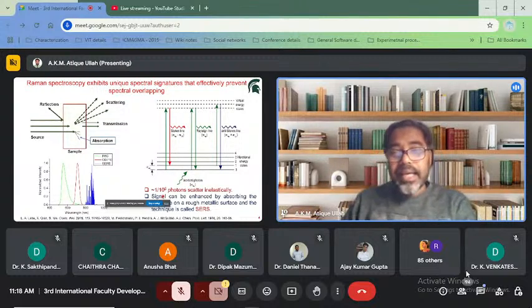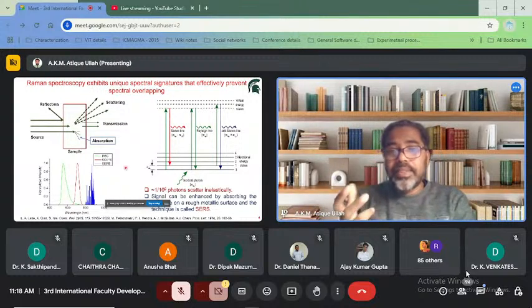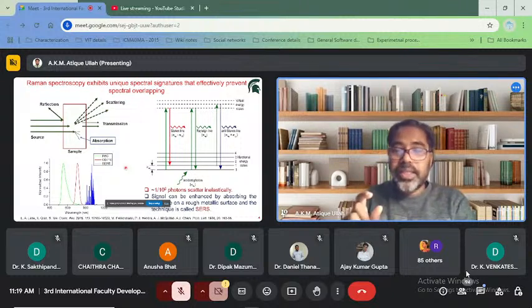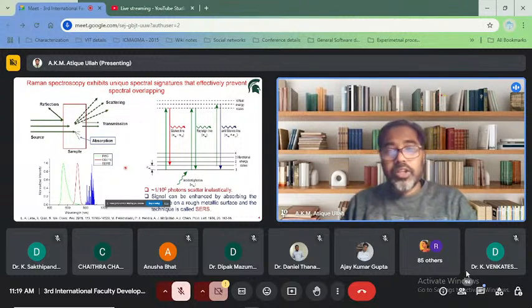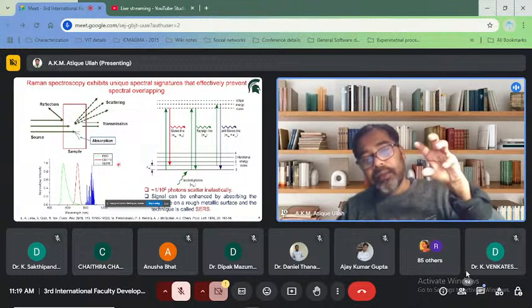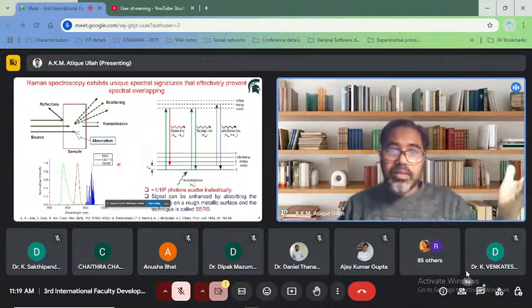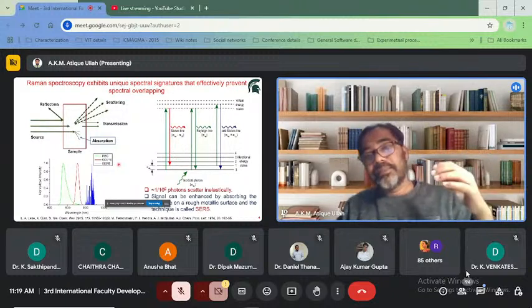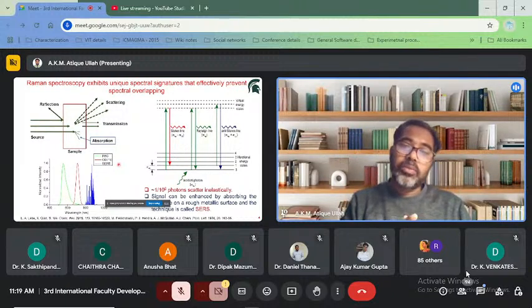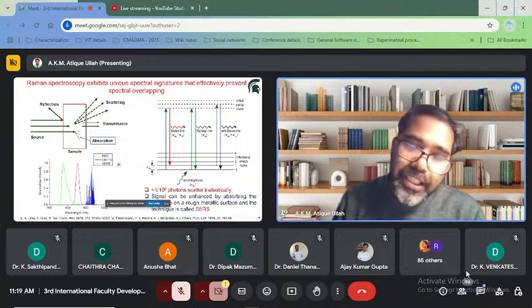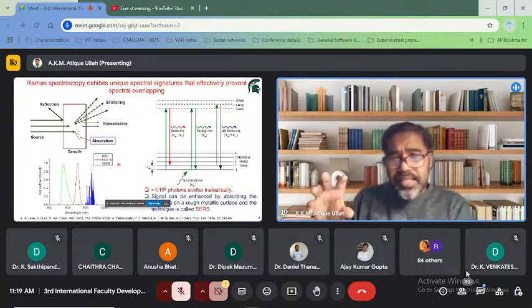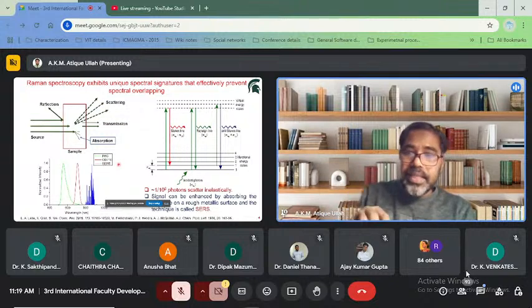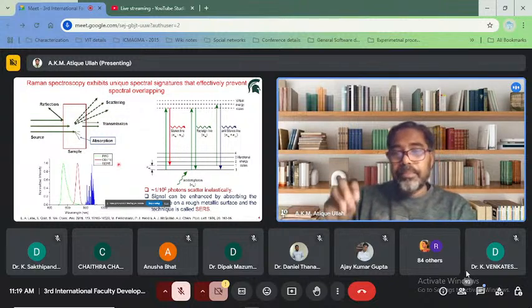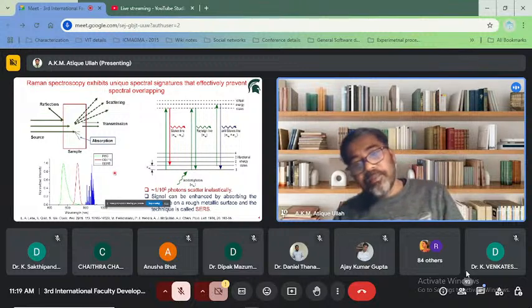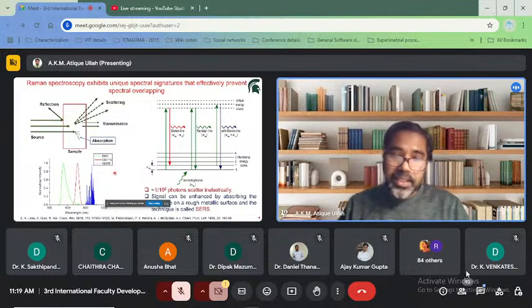This signal can be enhanced by certain techniques. If we put a Raman active molecule on the surface of certain nanoparticles such as gold or silver, the signal can be enhanced, theoretically by almost 10 to the 14 times. Since it is a surface phenomenon, enhancing the Raman signal by placing the molecule on the surface of a metal, it is called surface enhanced Raman scattering.